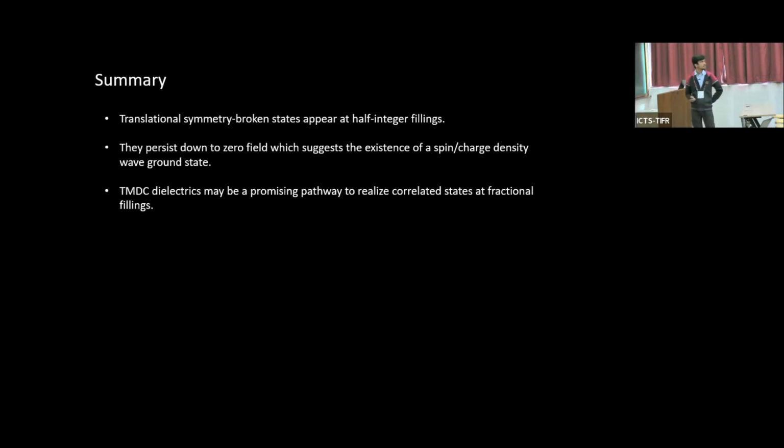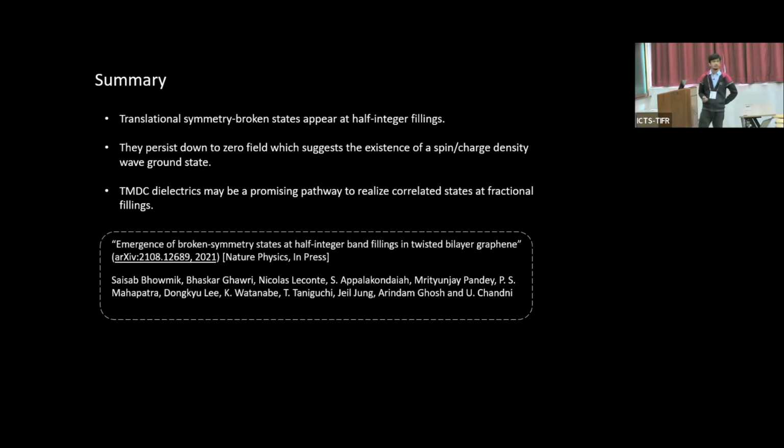Now to summarize, we have seen these states at half integer band fillings, which are driven by spin or charge density wave. We can't distinguish between the two, and they persist down to zero magnetic field. We believe that this is because of WSe2. So the use of this TMD dielectric may be a promising pathway to realize all these fractional fillings. For more details, please look at our paper.